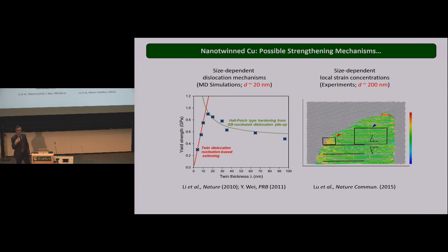There are basically two types of theories to explain this abnormal behavior. One relies simply on the nucleation of dislocation from perfect twin boundaries. And so we can predict some Hall-Petch type behavior here. And in this softening, it's now understood that twins can also nucleate dislocation from the junction with the grain boundary. So it's just a dislocation-based model. And then more recently,